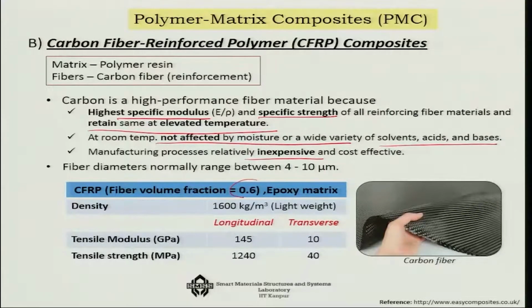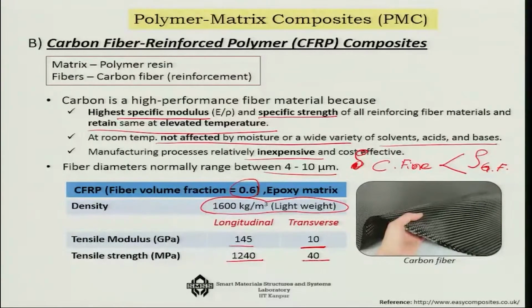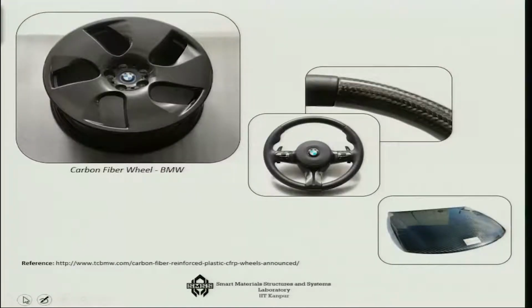With the same 0.6 volume fraction, and a fiber diameter of about 4 to 10 micrometer, you will achieve a density of 1600. That means carbon fiber is actually lighter in terms of density. The density of the carbon fiber is lower than the density of the glass fiber. So that is something very important. On the other hand, the tensile modulus is something like 145, which is very close to steel, double the aluminum. Highly anisotropic, the transverse is only 10 GPa, and tensile strength is 1240 MPa, transverse strength is about 40 MPa. This anisotropy is something one has to keep in mind while making a structural composite out of this system.